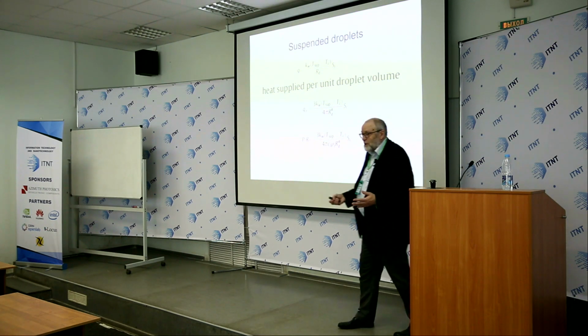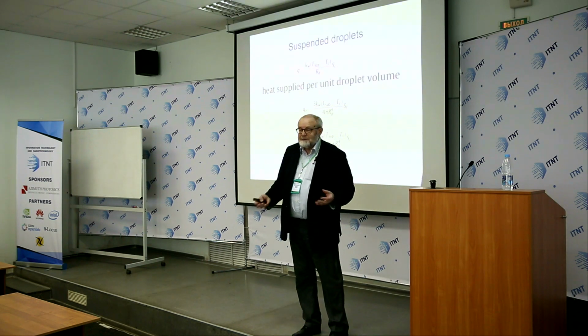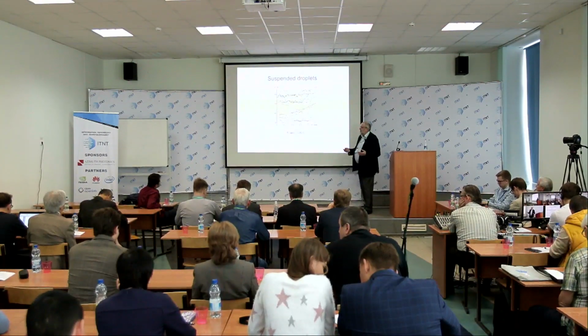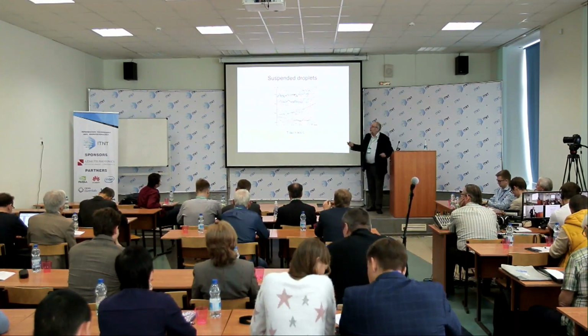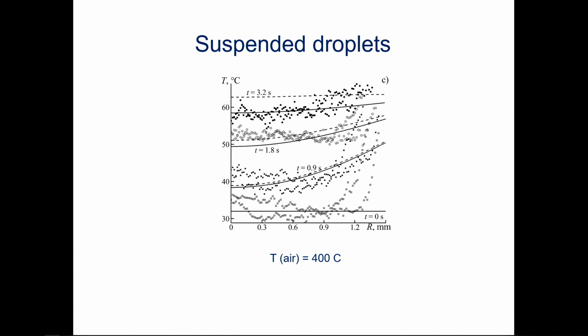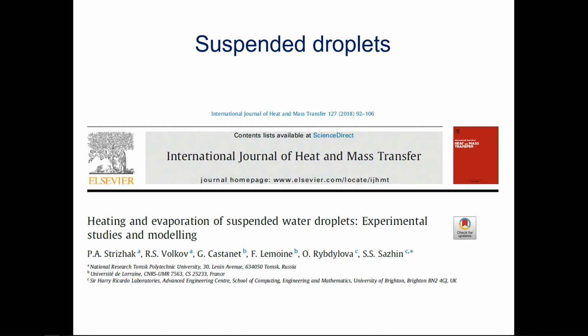So as you can see, we use the equation which was originally designed to take into account the effect of thermal radiation on heating of droplets, but applied to the case of the droplet, which is heated via the rod. And then once we have done this, we can get the plots of temperature versus distance from the center of the droplet. And we have, with a reasonable deviation between the results, reasonable agreement with experimental data. And these results were published in our joint paper with the colleagues from Tomsk University, and it was published last year.